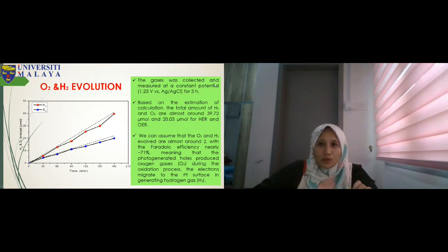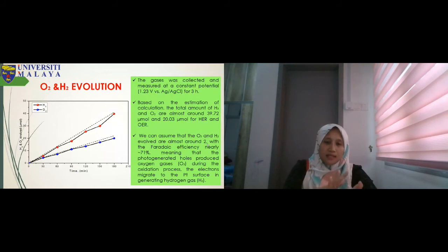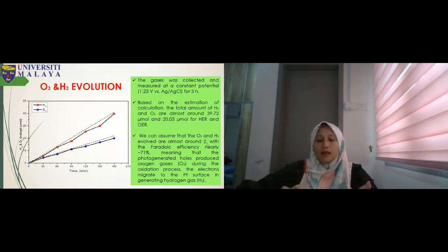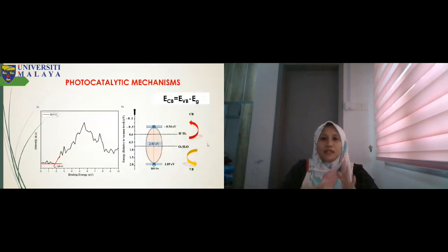And then the gas was collected and measured at a constant potential of 1.23 V. Based on estimation, we get hydrogen and oxygen of 39.72 and 20.03, and we can assume that the H2 and O2 evolve at around 2 to 1, which gives a Faradaic efficiency of nearly 71%. Meaning that oxidation occurs at our photoanode and the reduction occurs at the platinum. So this is the photocatalytic mechanism.